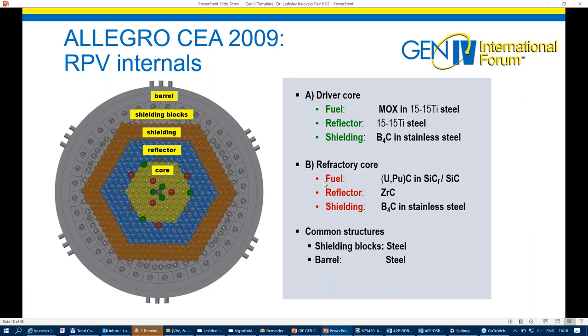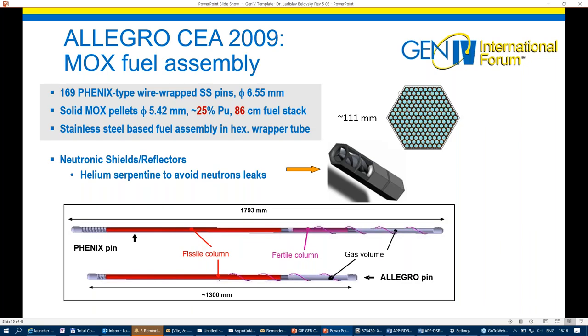Here you see the details on the driver core and on the refractory core. As you can see, in the first core, there would be a lot of stainless steel. So the stainless steel is one of the limiting factors concerning the outlet core temperature, just because the melting temperature of stainless steel used for these structure elements is something above 1300 degrees C. So this slide shows details of the MOX fuel pins and assemblies, very similar to the PHENIX design.